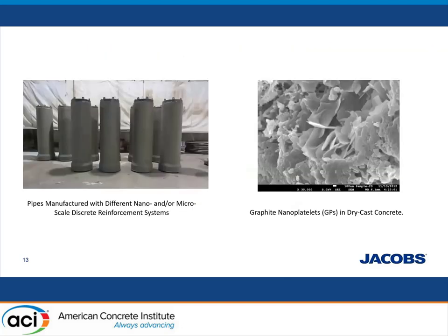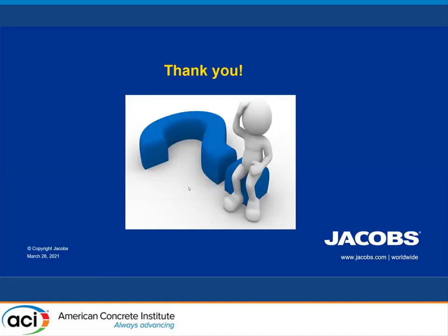To make a conclusion: graphite nanoplatelets at low dosage — 0.05 volume percent of concrete — were found to significantly improve the moisture barrier attributes and acid resistance of concrete, compared with plain concrete and PVA microfiber reinforcement. This improvement can be attributed to the tortuous diffusion path forced by closely spaced nanoplatelets of planar geometry, and also to the microcrack arrest quality of closely spaced nanoplatelets with high specific surface area and desired interfacial bonding to cement hydrates. That is all for my presentation — thank you.